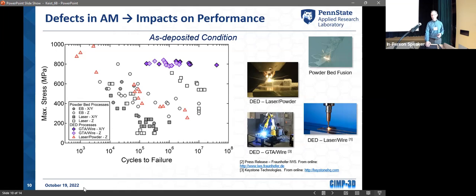Another popular way of building parts is what they call direct energy deposition. Again, it's layer by layer. In this case, you're directing the melt pool around the build block, and so you can make your component. But again, a lot of things can come up. The powder may get clogged, for instance. You may end up with defects. So what does that result in?